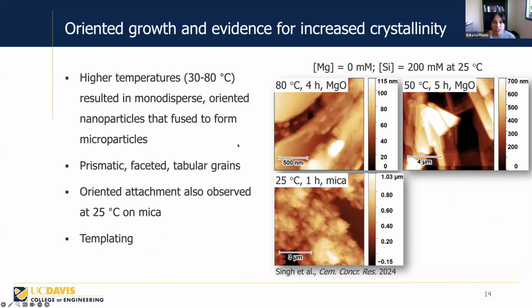We also observed evidence for oriented growth and increased crystallinity. This is at higher temperatures. So we get these oriented attachments of particles. Sometimes you observe more faceted grains that suggest a greater degree of crystallinity. And then if we use another substrate, for example, single crystal mica, we can observe this oriented attachment as well. This suggests a templating effect.